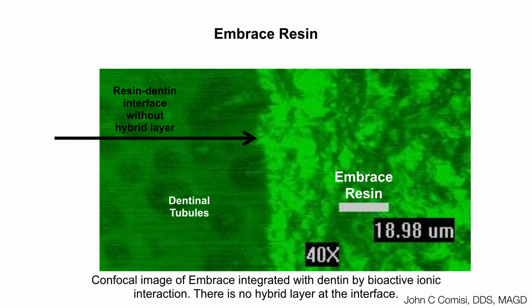First of all, the material does not create a hybrid layer as we are used to in our conventional materials. It creates instead an ionic interface with the tooth structure, not unlike that which is formed initially by glass ionomer materials. However, unlike GICs, this material releases calcium and phosphates, which, as we have seen from Jeffrey's work and as Sarah has previously stated, is important for apatite formation. As such, there is no MMP or enzymatic reaction. Both of these aspects to me are very important.